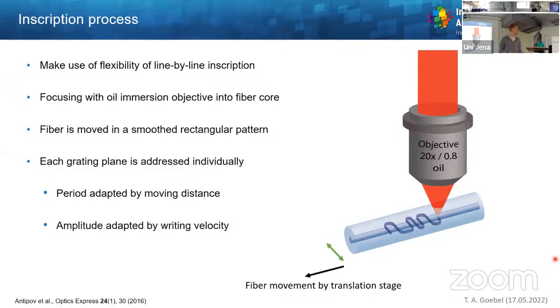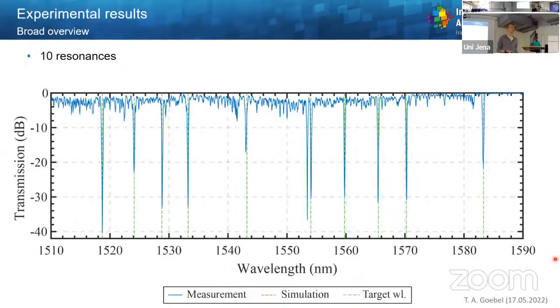Next, I want to show you a first result. Here is the transmission spectrum of an aperiodic fiber Bragg grating consisting of 10 resonances. The green dotted lines are the target wavelengths, and the blue line is the measurement. What you can see is that we are matching our resonance wavelengths very well. Also, the suppression factor is exceeded most of the time, only for the resonance at 1545, the resonance is slightly weaker.